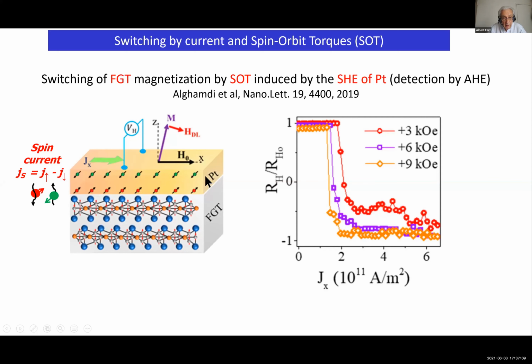So you can see the spin Hall effect in platinum corresponds to the deflection of the spin up and spin down, green and red spin, in opposite directions, so that the red spins are emitted downward, and the green spins are attracted upward, and so this corresponds to what is called injection of a pure spin current. What is this, my symbol for a spin current? Electrons with opposite spin going in opposite directions into FGT. And so you know that injecting a spin current into a magnetic layer induces a torque, what is called a spin orbit torque, and is used also in three dimensions to reverse the magnetization of a magnetic layer.